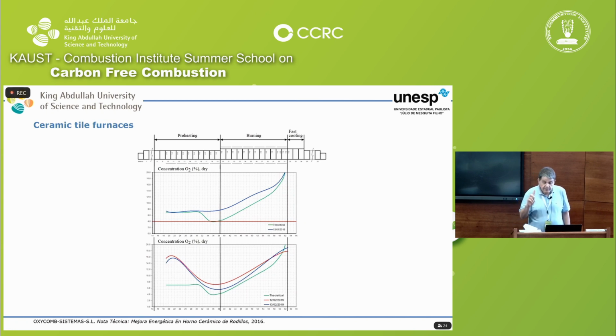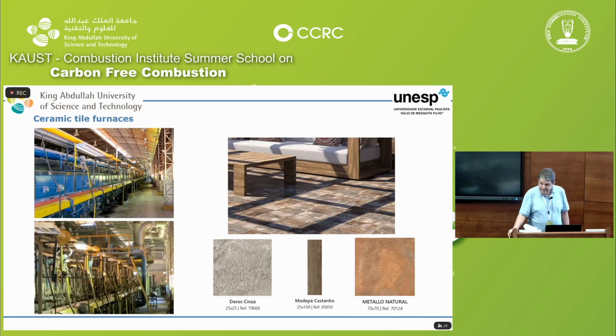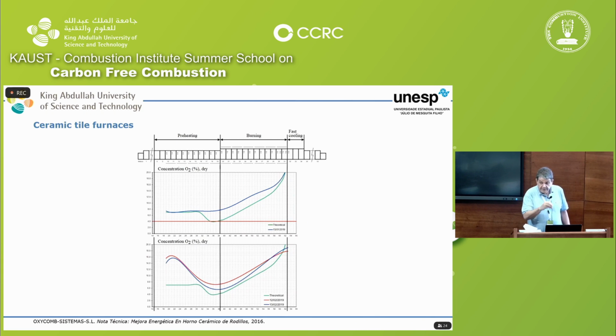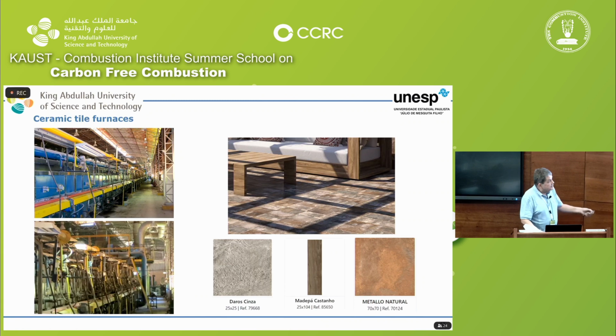But there is a problem. What's the problem? Let's go back to the nice pictures in here. You see, the one on the left here is a small tile for the floor. It's small, 25 by 25. No, it's 25 centimeters. Yeah, and the other one is 70 by 70. This one is 25 by 104. So what happens is that the heat requirement changes. So it's almost impossible to have an economic furnace if you don't have this type of control that the students did in there. Automatic for each set of tiles that you're fabricating. You see, this is very nice.